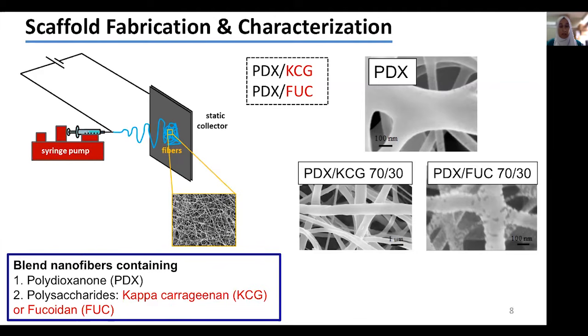And we can see from the images on the right-hand side that all the fibers were very smooth and there were no surface protrusions. Now, if we look closely at the scanning electron microscope image shown on the lower right-hand side, we note the presence of a second component for the fucoidan-containing fiber. And this is very likely due to the presence of fucoidan on the surface of the fiber.